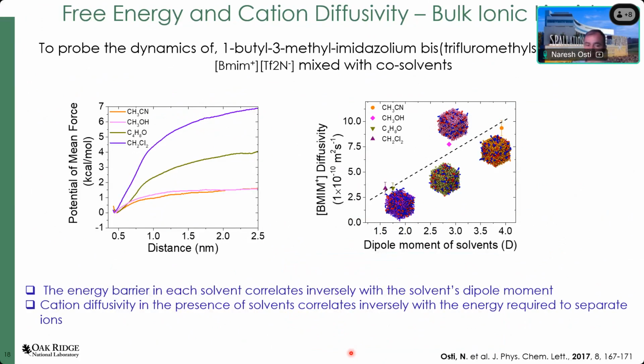Now, the very first thing we started to look into was the potential of mean force required to pull the ions apart in the ionic liquid and organic solvent system using MD simulation. We show that you need very little force to dissociate the ion pairs when you have a solvent with a high dipole moment. It scales nicely with the dipole moment of the solvent, and we were able to extract the mean square displacement of the ions, from which we calculated the diffusion coefficient of the cation of the ionic liquid using MD simulation. You can see a strong trend of increasing diffusivity as you go to a higher dipole moment of the solvent. This is the MD result.